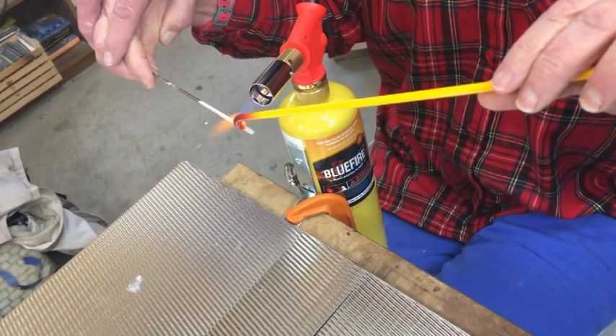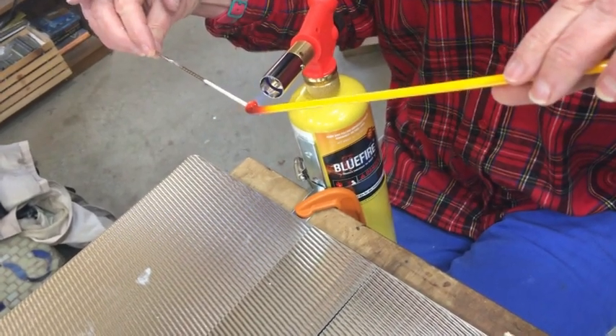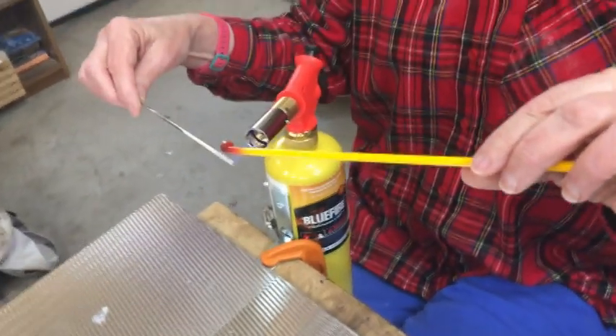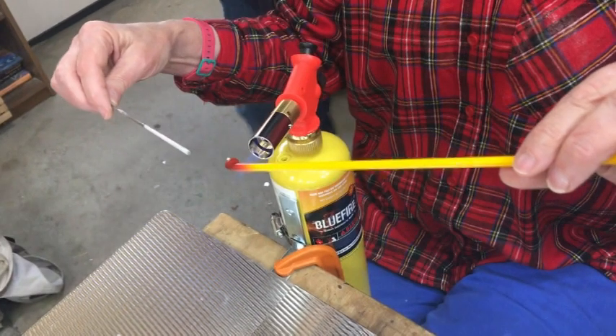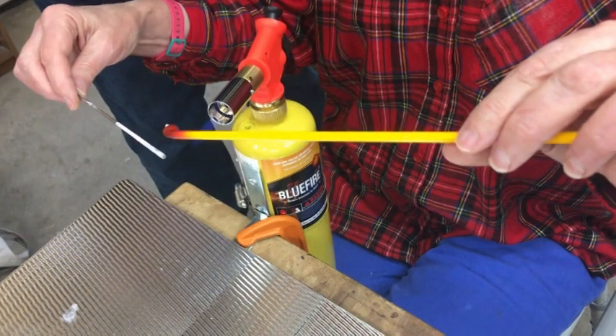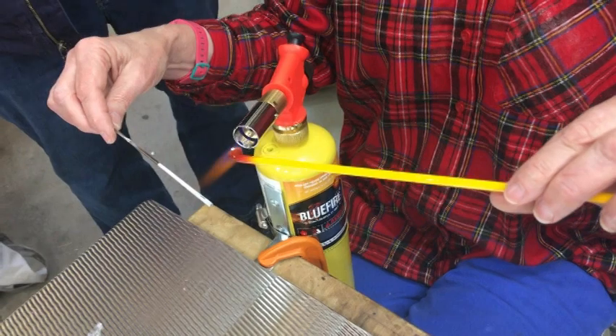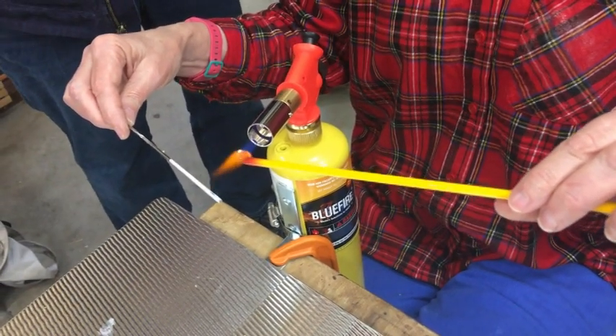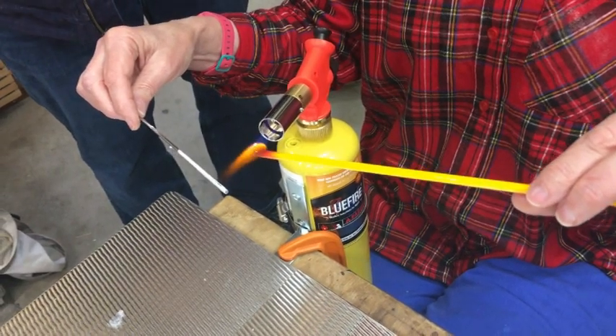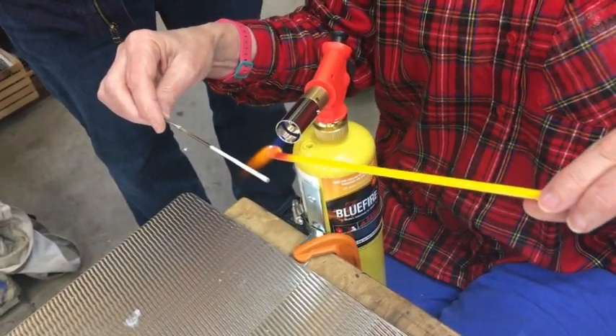There we go. Now roll that mandrel rod. Roll. Nope, we stuck it too close, and we lost our heat. Some of the bead release came off, so you don't want to put it on that spot because it would stick to the rod. Get that glass hot again. The bead release is very fragile. You can't force it onto the rod. You have to just let it drip onto the rod. It has to be liquid.